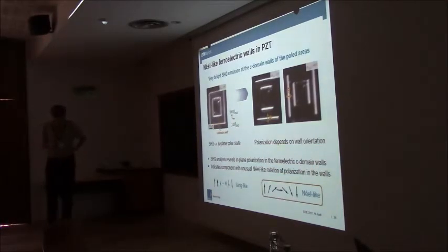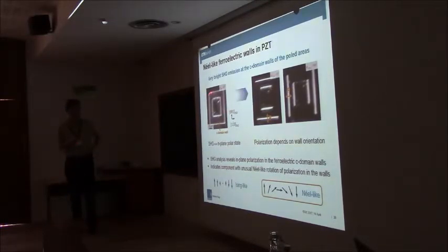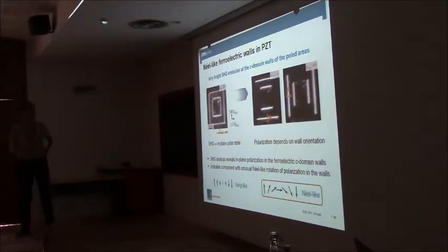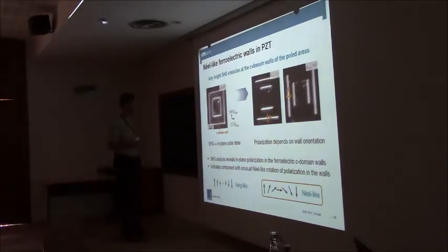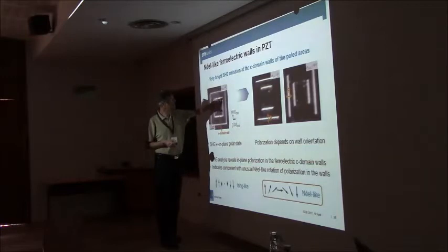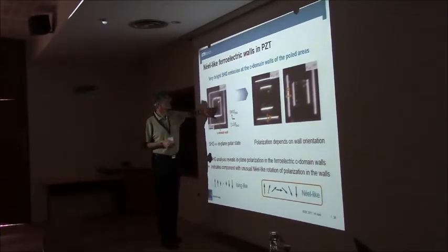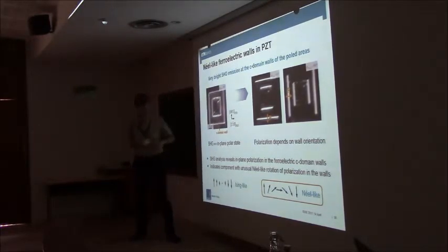Okay. Then one very outstanding aspect of these pictures is that there is this extremely high brightness that you have at the edges of the areas that you have polarized in one or the other C direction. So why would there be such a bright second harmonic emission? In principle, in this configuration, you should not see any A domains. That's why everything is black. So you could suspect, maybe in your domain walls it's not C domain here. Maybe there is an A domain that you see and that it's generating the light.